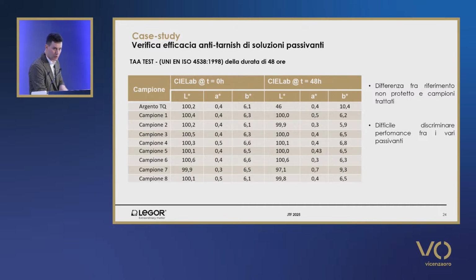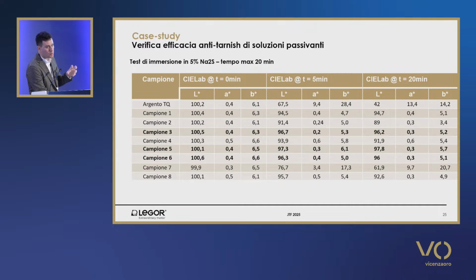These are the results after 48 hours. And what emerges here is that there is certainly an anti-tarnish effect in the passivating solutions tested, because we see the difference in color between the non-treated product and all the other products. But it is impossible to differentiate the efficacy of the various treatments, because all the compounds have had good results, and it's difficult to say what is the best sample.